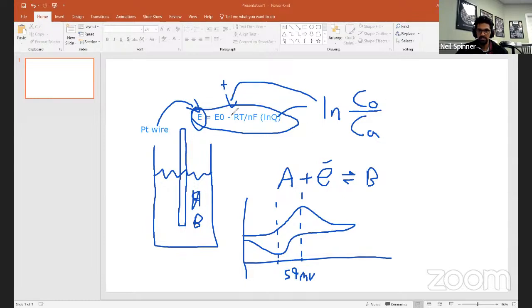Nernst equation. When you actually plug in all of these, somewhere in the middle here you have it where these two concentrations are equal to each other. So you get ln of 1, which is 0, and E naught is where the concentrations of these two are equal to one another. So somewhere in the middle here, you have E naught. This difference is really just a manifestation of the Nernst equation. When you convert the natural log to log base 10, a constant comes out, and when you multiply these numbers by it, you get 59 or something along those lines, 2.303 something. And hence you get this difference of 59 between the anodic and cathodic waves.